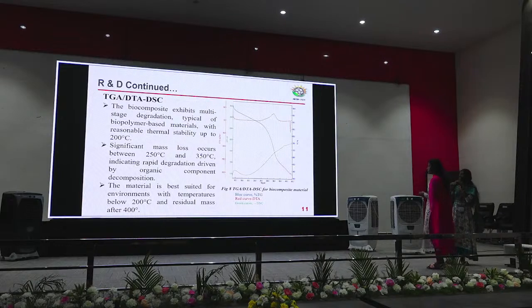TGA, DTA and DSC. TGA is represented by the blue curve, DTA by the red curve, and DSC by the green curve. TGA is used to analyze the mass loss. Up to 100 degrees Celsius, it is stable with only moisture evaporation. It can withstand up to 200 degrees Celsius.